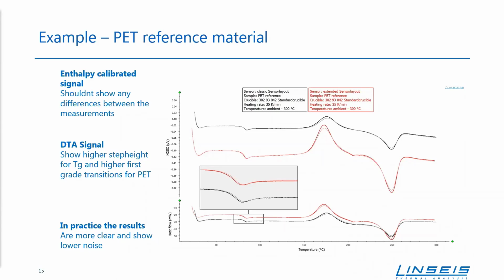But what you can see there is the red one. So the new prototype, the extended sensor layout, is much clearer without any noise there. And in comparison, if we zoom in that much, we can see there is some noise on the classic sensor layout. And this is what we want to see here because, for example, we use just 10% of this sample, or we use another sample with much smaller transitions. So then it would be hard to detect these transitions. And in this case, smaller noise is pretty important for a clear evaluation of our signal here, of our transition. So yeah, for a clear visibility, this is pretty important, and this is exactly what we want to see. The enthalpy of the sample, of course, is still the same, but the visibility of our transitions is much better.